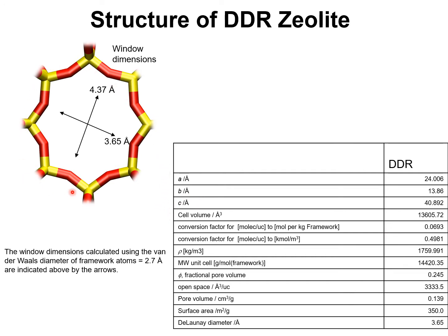This shows the dimensions of the 8-ring windows separating cages. The smallest distance is 3.65 angstrom, and the longest distance is about 4.4 angstrom. Further structural details of DDR zeolite are provided in this table. These are the unit cell dimensions A, B, C, pore volume, surface area,